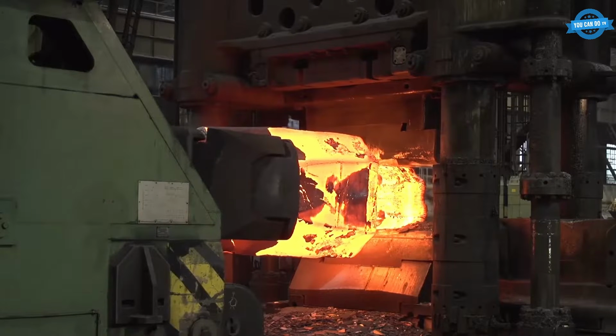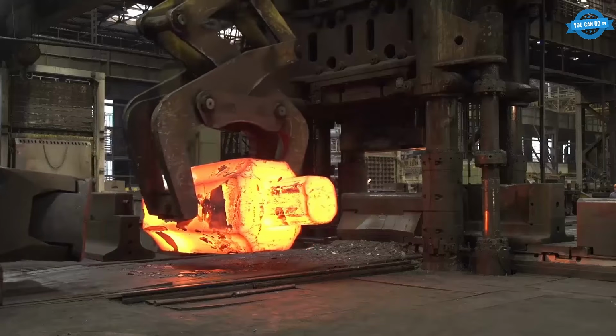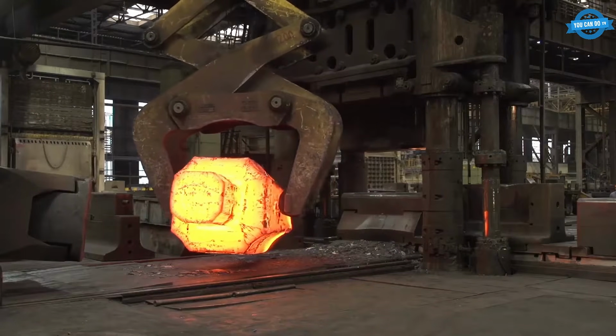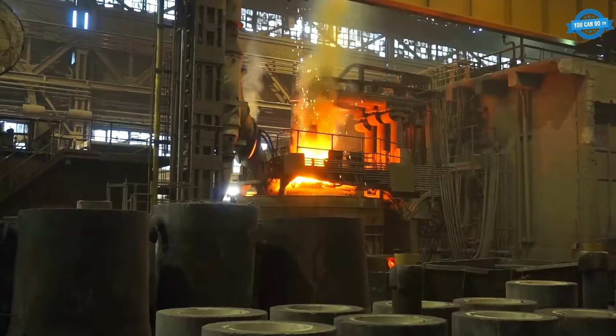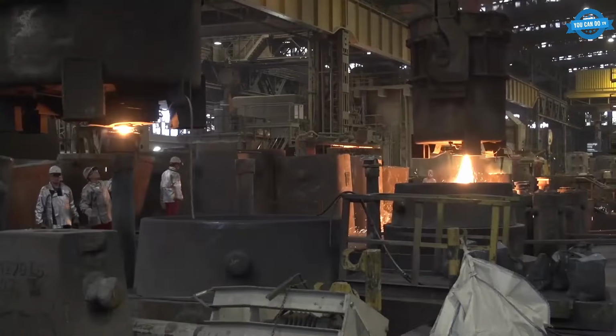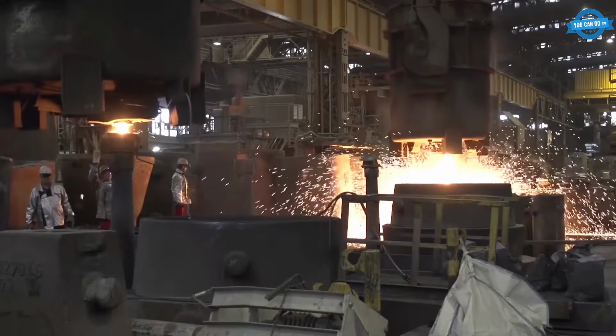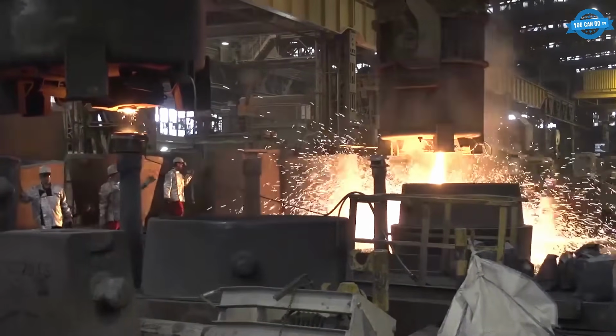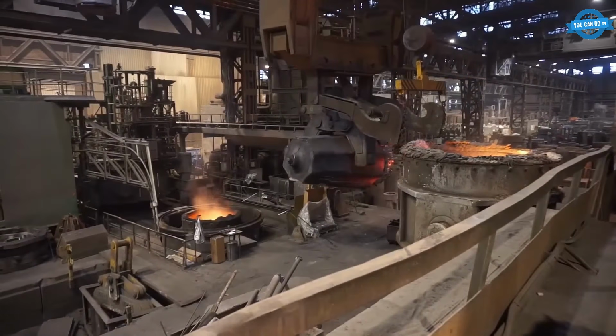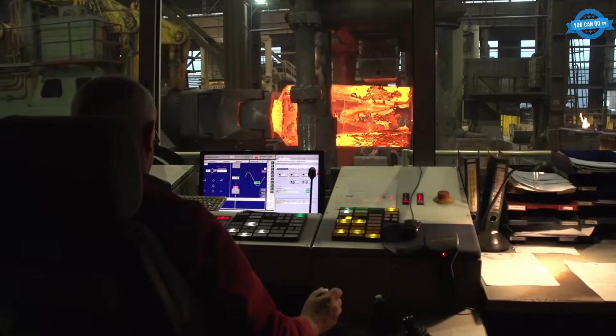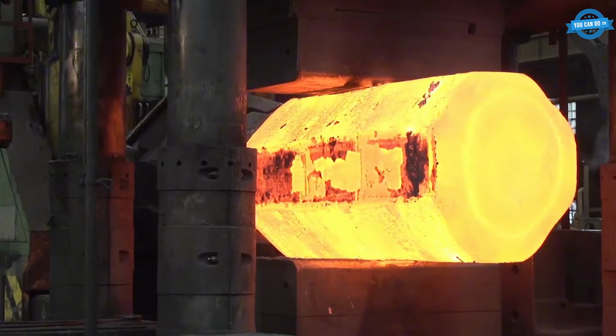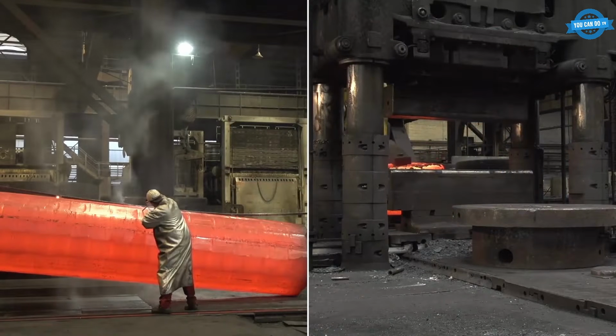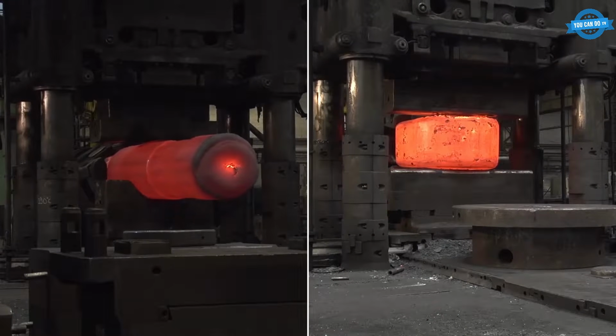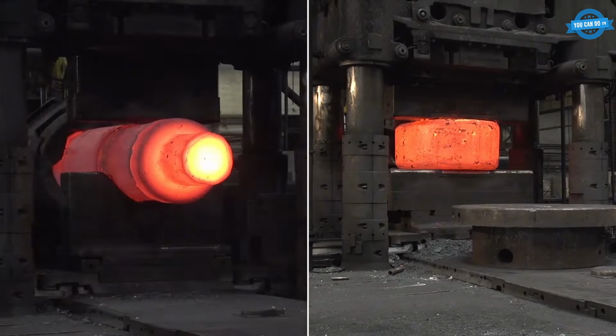Free forging is where you go when the part is so big or so critical that a die can't survive making it. The ingot starts life in an electric arc furnace, holding up to 50 tons of liquid steel per heat. After ladle refining and vacuum degassing, it gets cast. The largest ingot runs 76 tons, poured from 2 heats combined. A 76-ton ingot is basically a small building tipped on its side, and they cast it in one go.